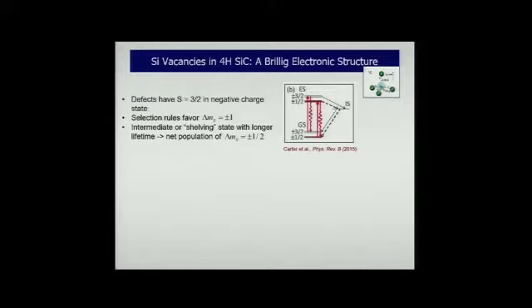Whereas what is different is if we do an excitation from the plus or minus 3/2 to excited plus or minus 3/2, there is similarly an interaction with the shelving state, but the lifetime of the electron from the plus minus 3/2 to the shelving state is slightly longer. What that means is that just because of the dynamics of the lifetime and the dynamics of the transition, there is inevitably a slight over time preference for the population of plus or minus 1/2 states in the ground state.